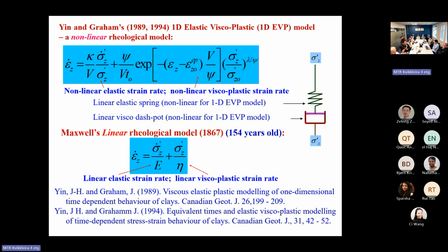For my results, this is for a static test. I mean, it's loading and unloading, but not frequent unloading and reloading. That's related to your cyclic loading, and you will see later my unloading and reloading curve is the same line. But on cyclic loading, you can normally see a loop. So I consider cyclic loading can add another factor to the stress-strain time-dependent behavior.